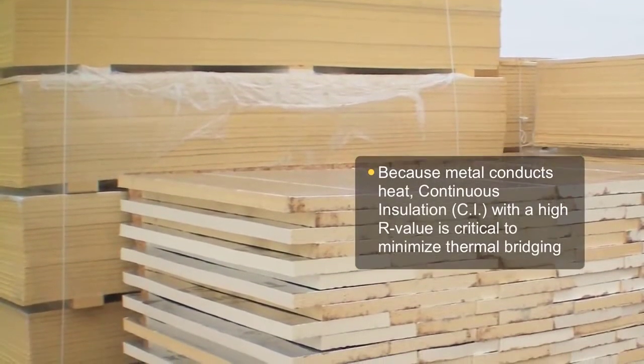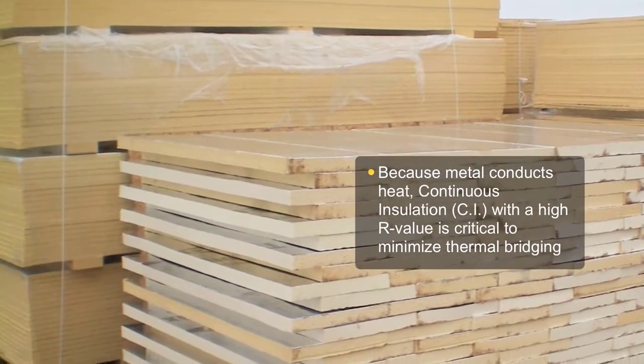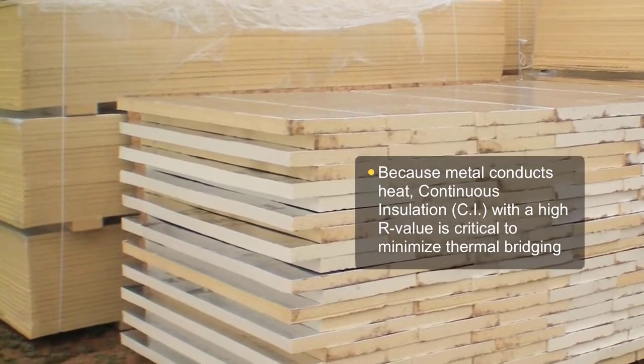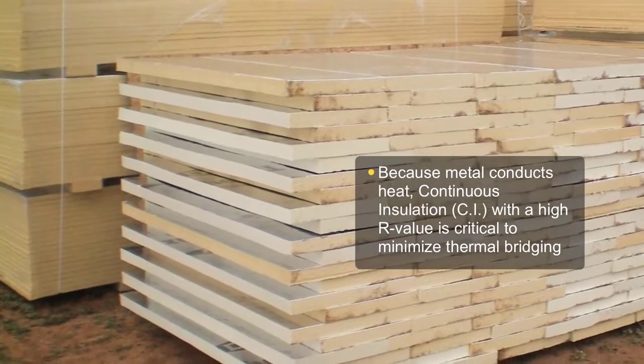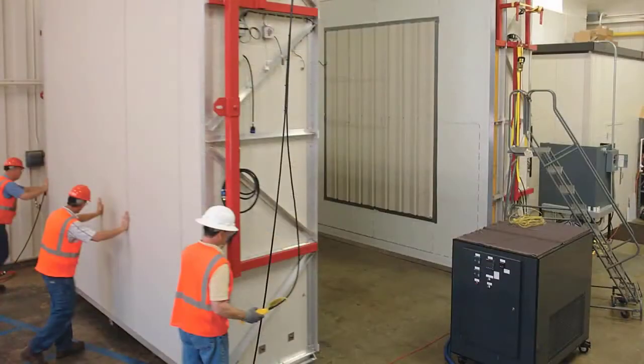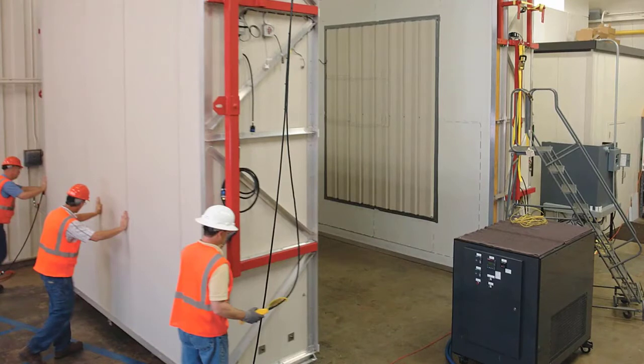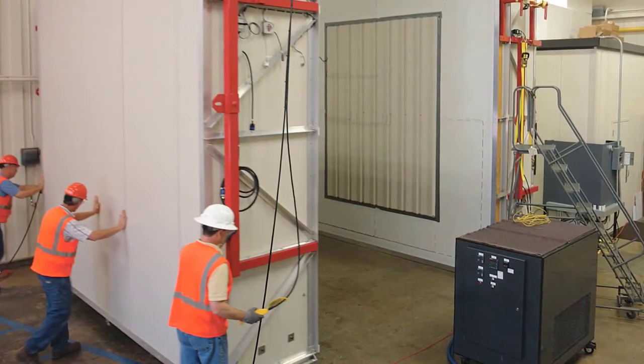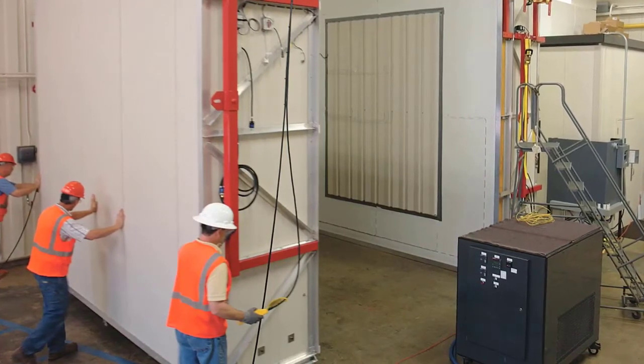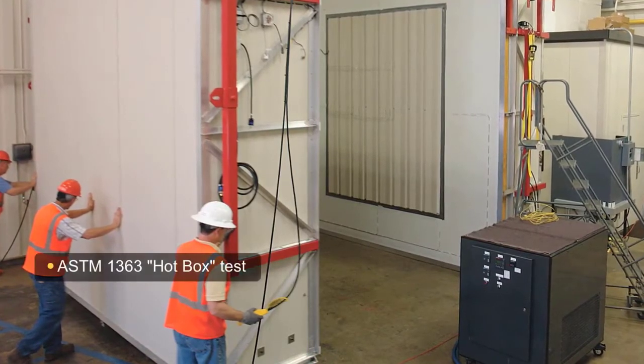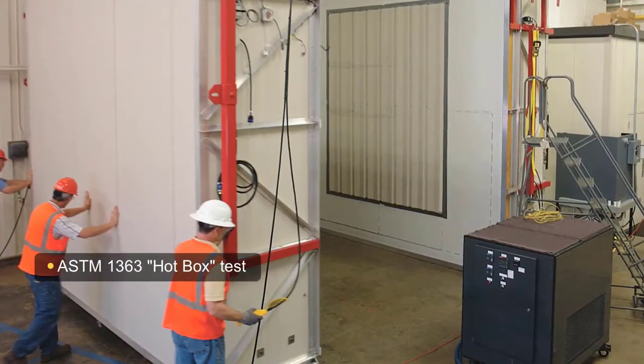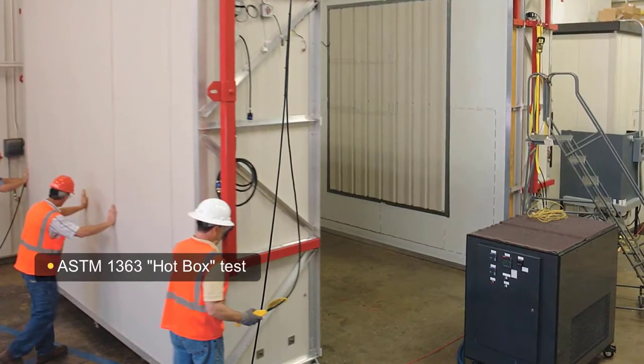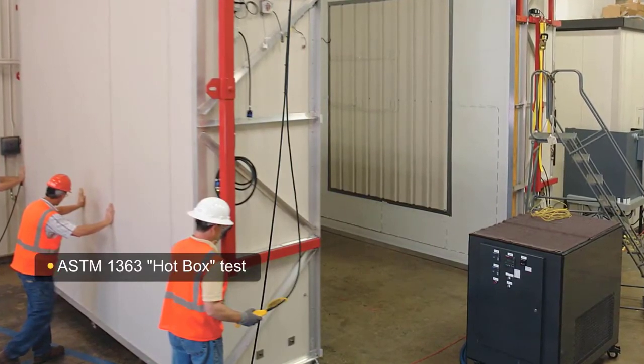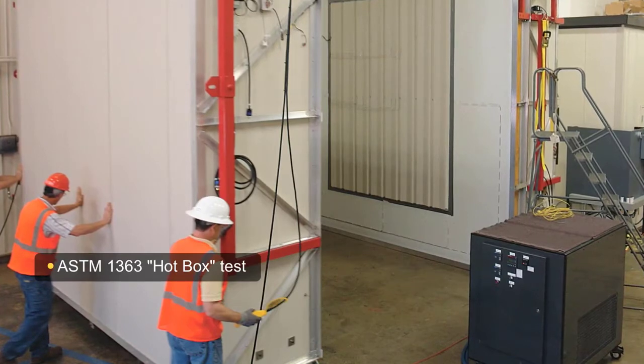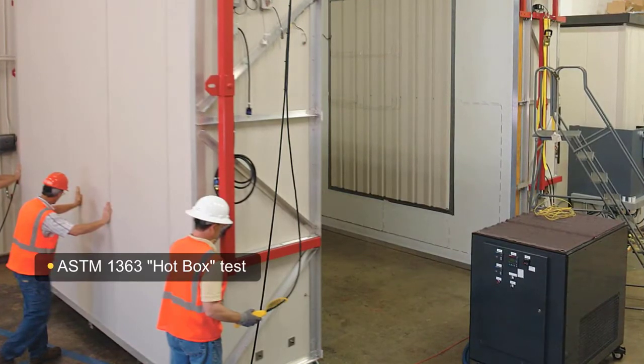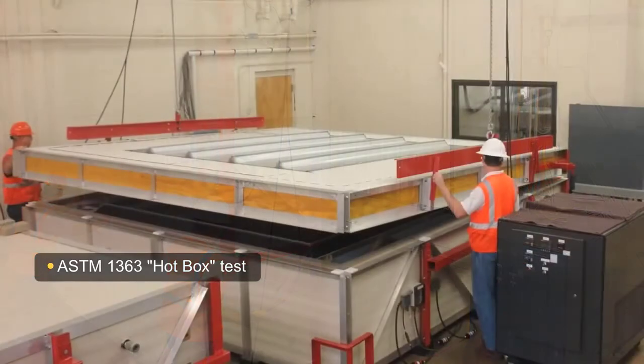Metal is a conductor of heat. As a result, installing continuous insulation with a high R-value is a critical component, helping to minimize the effect of thermal shorts. Recent research at Oak Ridge National Laboratory focused on the thermal performance of new and innovative insulated metal roof assemblies. Using the ASTM C1363, or hotbox test, this work provided an indication of the relative efficiency of the insulation and provides guidance to designers on what assemblies more closely match the calculated value of the insulation used in the design.